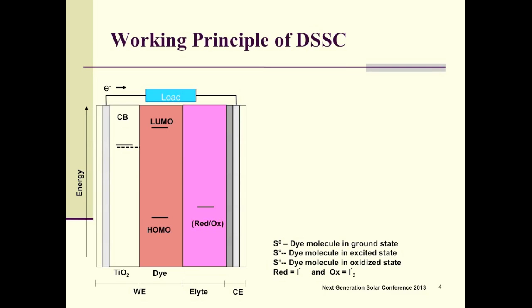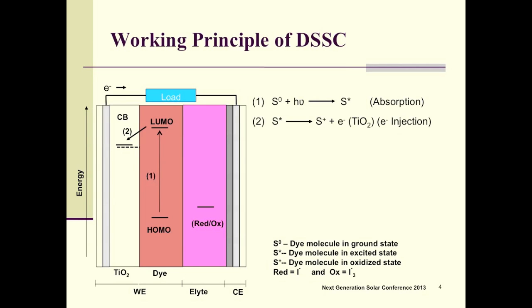So in terms of the working principle, an incoming photon is absorbed by the dye molecule, and an electron from the HOMO of the dye molecule is excited to the LUMO of the dye molecule. From the LUMO, this electron is injected into the conduction band of the TiO2, leaving behind the oxidized dye molecule. In nanoporous TiO2, this electron percolates and finally reaches the transparent conducting oxide.